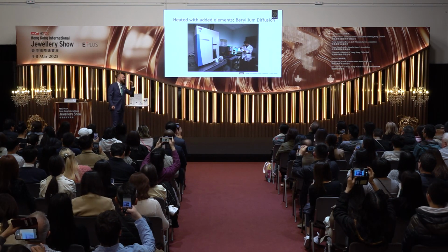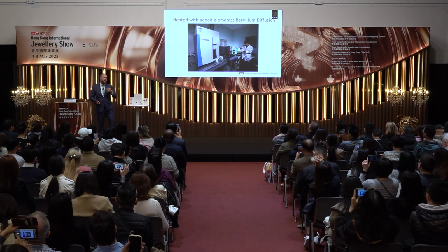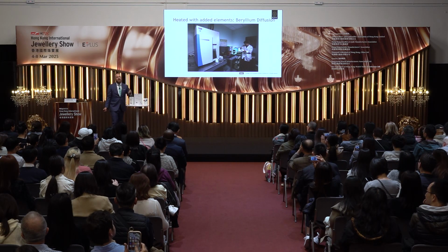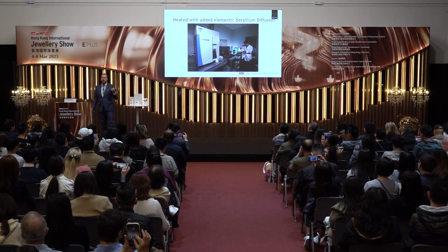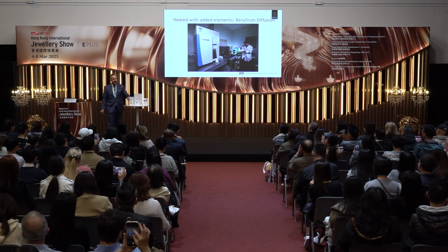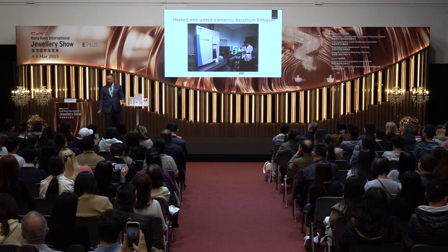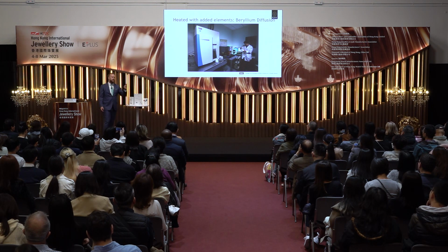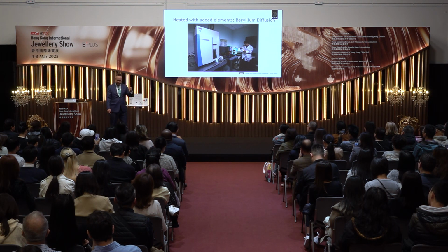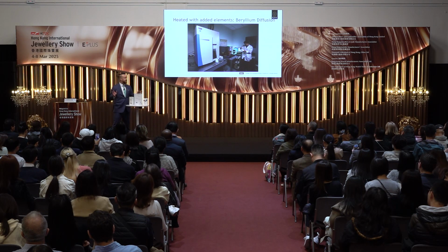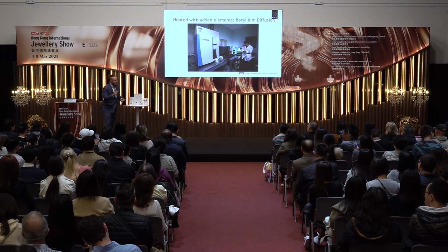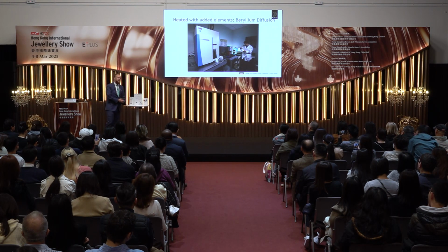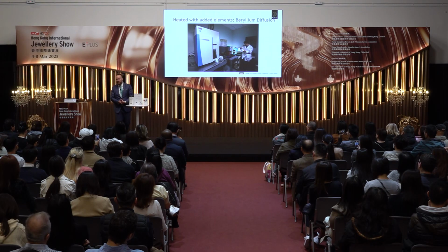There is no indication in the inclusions, in the color zoning, in the FTIR spectra, in the UV-Vis spectra that you can use. The only way that you can detect beryllium in a corundum is by measuring the actual beryllium in the corundum. So at GIA, we use an instrument called LA-ICP-MS, laser ablation inductively coupled plasma mass spectrometry. That is not going to be on the test.